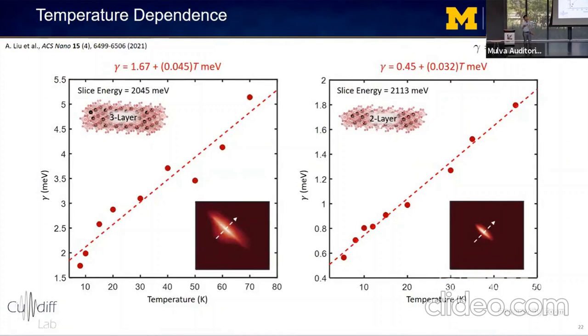So to extract the thermal broadening parameter A, we took measurements of the homogeneous line width as a function of temperature, which unsurprisingly exhibit a linear dependence on temperature due to the predominant coupling to acoustic phonon modes. And linear fits to the data are shown as the dashed red lines, as well as the equations on top, which show that the thinner 2-layer nanoplatelets exhibit both a narrower 0 temperature line width of 0.45 meV compared to 1.67 meV, as well as the reduced thermal broadening parameter of 0.032 meV per Kelvin versus 0.045 meV per Kelvin for the 3-layer nanoplatelets.